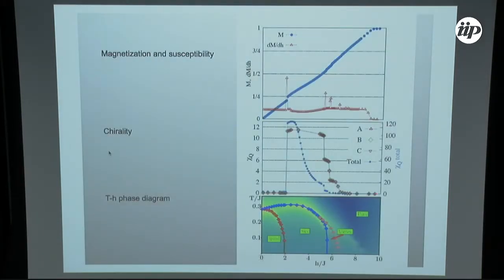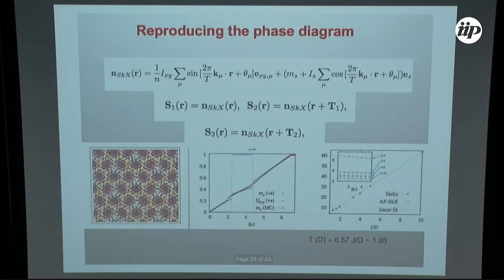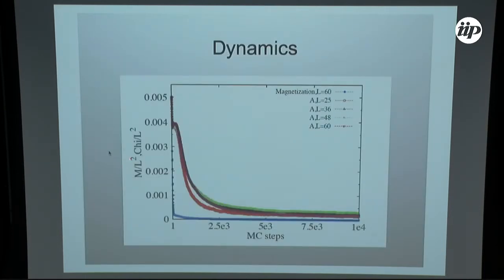You see here, I will now fix some magnetic field in this region, in order to have these lattices of Skyrmion lattices on each sublattice. Then I will turn off the magnetic field, the quenching, and see what happens with the different quantities. This is Monte Carlo steps. As soon as you turn off this magnetic field, the magnetization, in blue, drops to zero immediately.